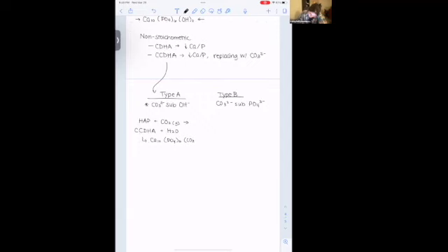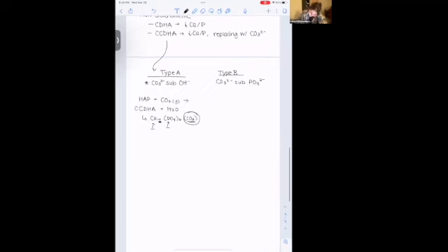So that actually ends up looking like this with the carbonate molecule. And again, because it's calcium deficient, you probably actually wouldn't have this as 10. It would also be reduced compared to the amount of phosphate you have. But the key piece is where this carbonate is being replaced. And most of the time you actually end up with type B rather than that type A because it requires that high temperature.